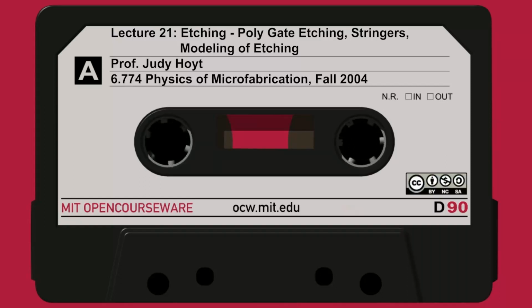Here's an example where they tried to do the siliciding with cobalt, in the upper SEM micrograph here. It didn't work too well. As you can see, the cobalt went down in. It didn't make it to the bottom. In fact, what happens is the silicon got sucked up. And next time we'll talk about silicide reactions. The silicon was actually moving, and you ended up with a big void. So you had no gate in this example.